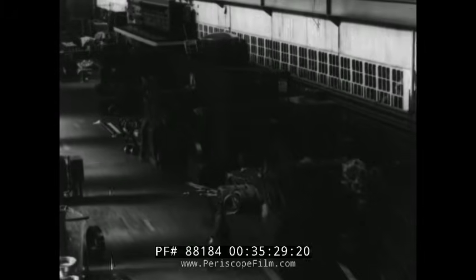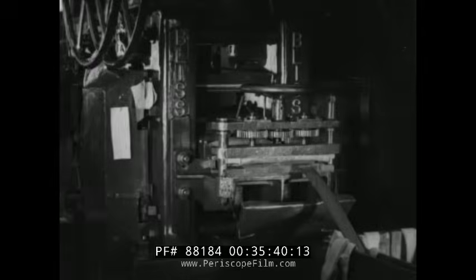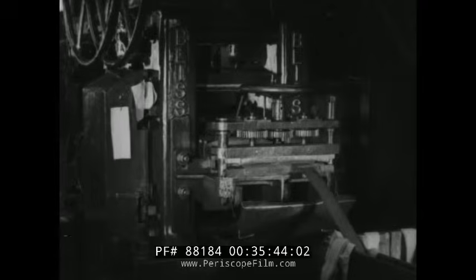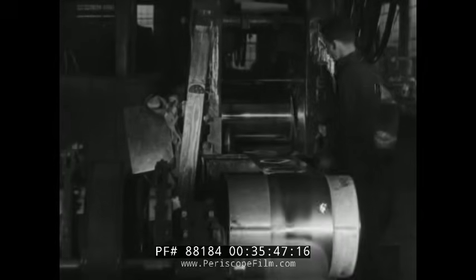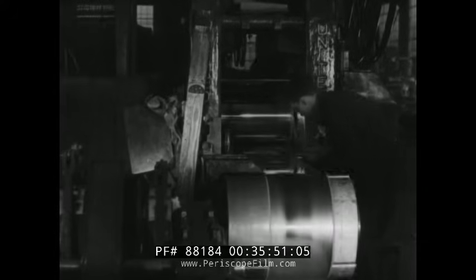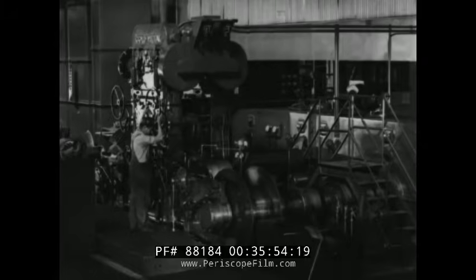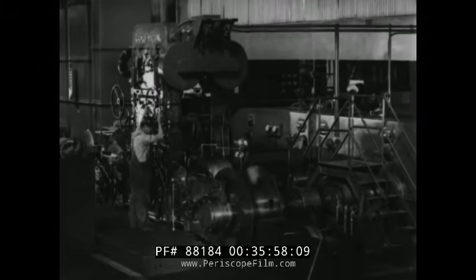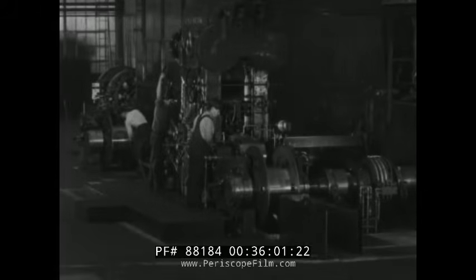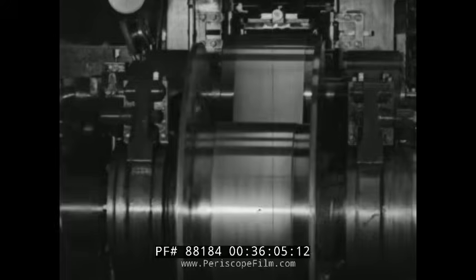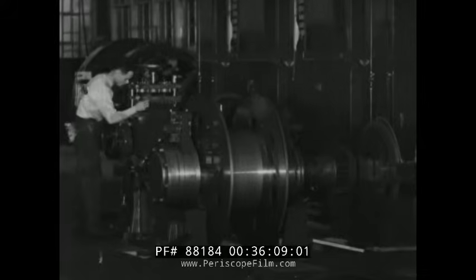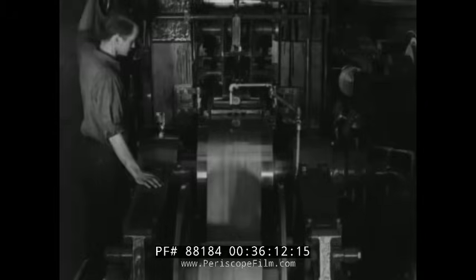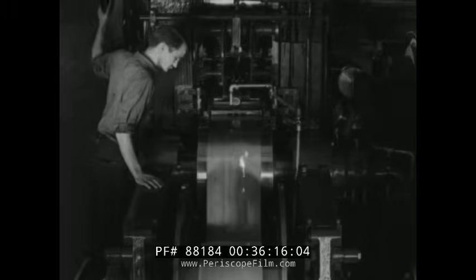Strip is cold rolled in a department by itself. Mill train handles ordinary production. The end stand is called the finishing stand. The strip from the final pass is carefully checked for gauge. The heavy reductions and close tolerances required in nickel alloy strip rolling have made it necessary to install a high-pressure cold mill. In the Steckel mill, the strip is pulled through the rolls. The steps in process are carefully checked. Controlling devices enable this mill to meet very exacting strip specifications.